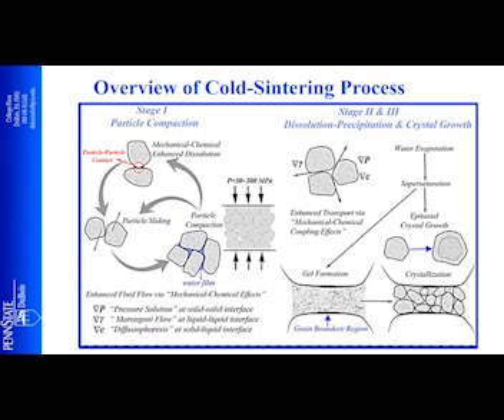So in the case of metals, of course, we don't expect them to be sintered at that low temperature. However, this method gives you properties which are much better in compacted parts. So if you think about what happens during the cold sintering process, which is usually done under pressure and temperature over time, there are several stages, but what you find are several multi-mechanisms with coupling effects from mechanical and chemical. Yes, there are usually hydrothermal reactions which happen.